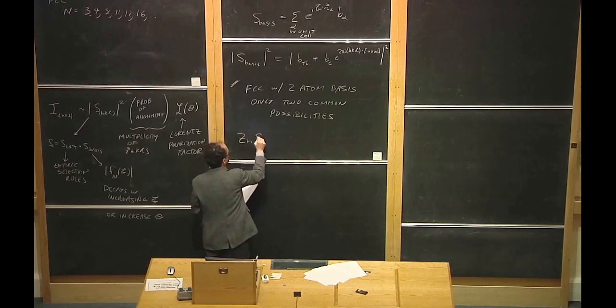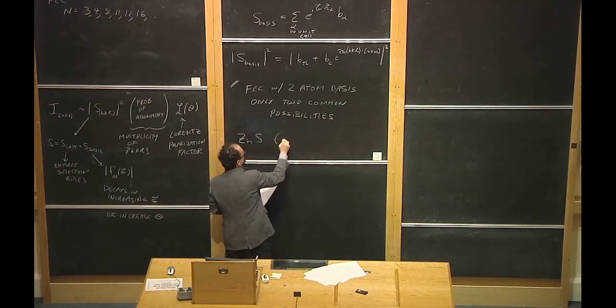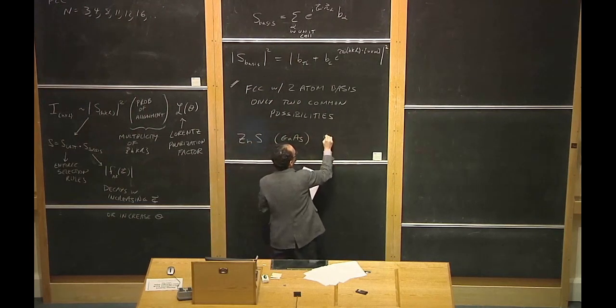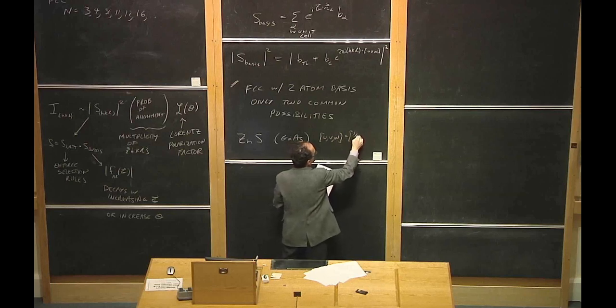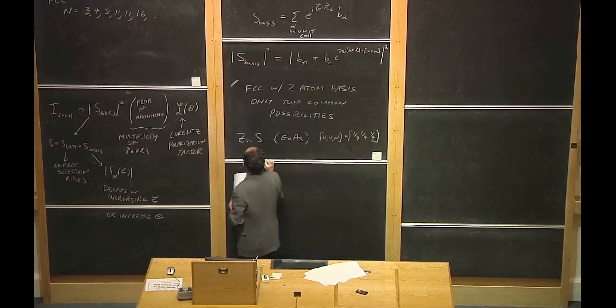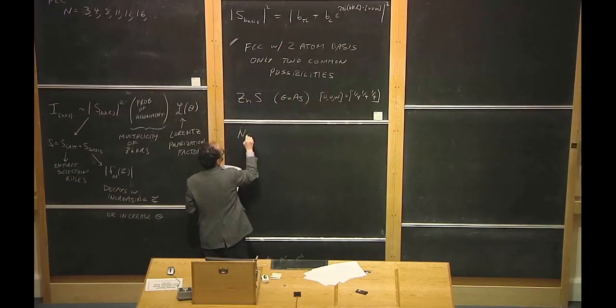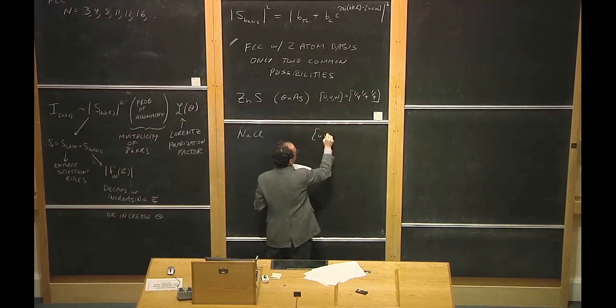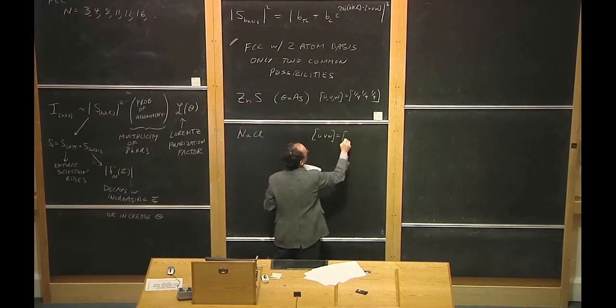There's a so-called zinc blende structure, which is the same as the gallium arsenide structure, which we talked about in class, which puts UVW at the position 1/4, 1/4, 1/4. And the other possibility we also discussed is the sodium chloride structure, which has UVW at 1/2, 1/2, 1/2.